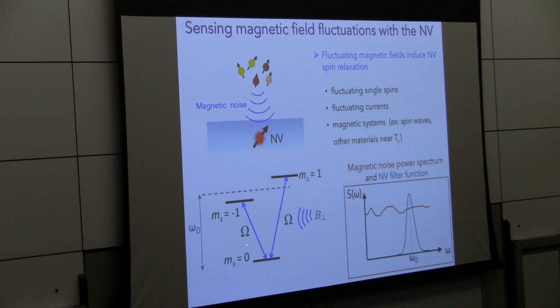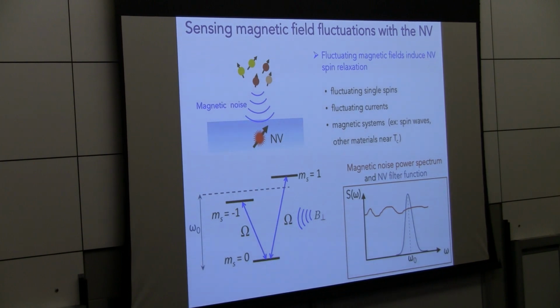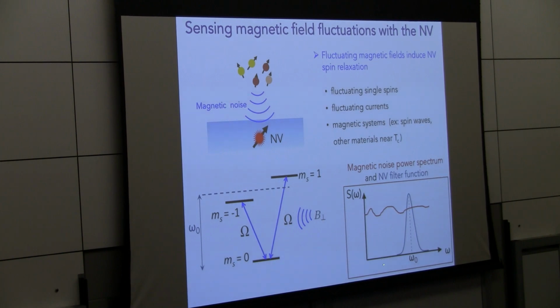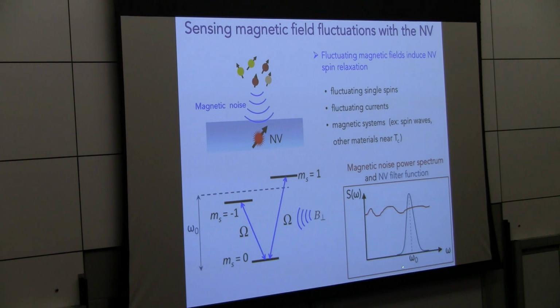And so that's what I'm trying to show here, if I draw my NV, my three-level system. This omega, I'll call that the relaxation rate, meaning if I were to polarize my spin system into this state, how long would it take for the population to thermalize into some thermal mixture of, say, the 0 and the -1 state? That rate omega is sensitive to the fluctuations at this frequency omega naught. So if I have some noise power that the NV center feels, and I monitor the relaxation rate, this T1 time, effectively that acts like a filter function centered exactly on this frequency omega naught.